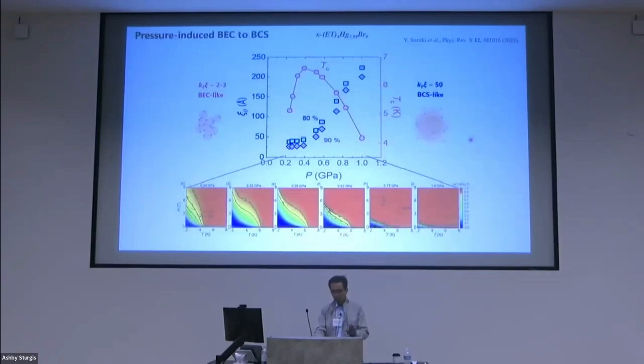Okay, we are moving to the superconducting properties. As a function of pressure, we extracted the coherence length from the upper critical field. This is the color plot of resistivity. Blue color shows vanishing resistivity, superconductivity. Red color shows normal resistivity. From the slope, we extracted the coherence length. The coherence length depends on the definition of 80% recovery of resistivity or 90% recovery, but the difference does not matter. The coherence length at the low pressure range is several angstroms, and one order of magnitude larger at high pressures.